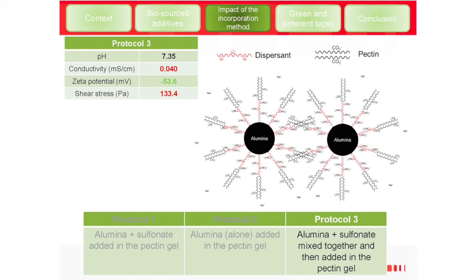Last protocol: we mix the alumina with the dispersant first, so there is adsorption of the first shell of dispersant around the particle, and then we add the pectin. So the pectin attaches to the dispersant. This means you have a huge shell of organic molecules around the alumina powder, and the result is a very thick suspension. Despite the fact that the potential is good, it's too thick a suspension which cannot be tape cast.